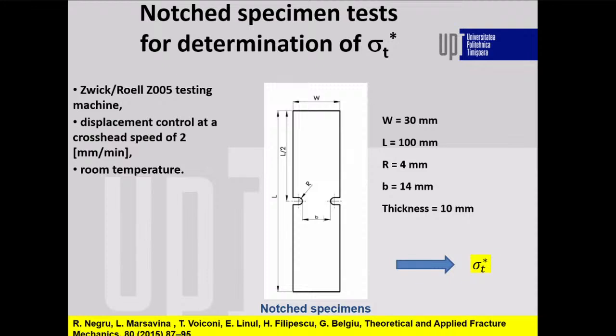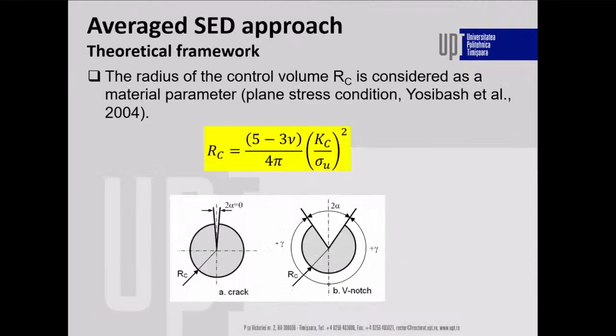The tests were performed in the classical manner, in displacement control with 2 millimeters per minute crosshead speed and at room temperature. In this presentation I will use only cracked specimens, so the control volume is circular, and we use the Yosibash relationship for plane stress condition to determine the control radius.